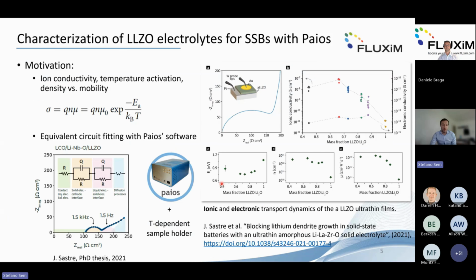Some of our products were already used for the characterization of batteries. For example, Paios was used together with a temperature-dependent sample holder in the study shown here. I will not go into details about the study, but the impedance module of Paios was used for the characterization of batteries. Specifically, it was used to estimate the ion conductivity, its temperature activation, and the density versus mobility. Additionally, the equivalent circuit fitting from the Paios software was used, so that the impedance of the battery can be fitted with several circuit elements, and the characterization can be properly done.